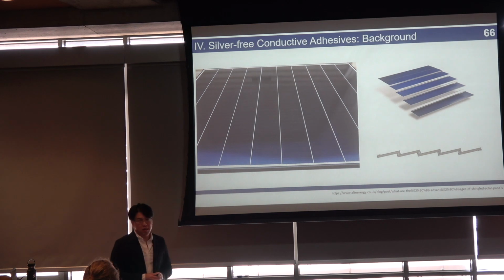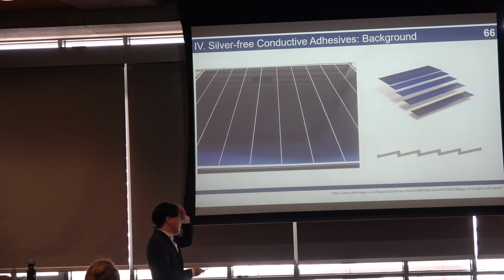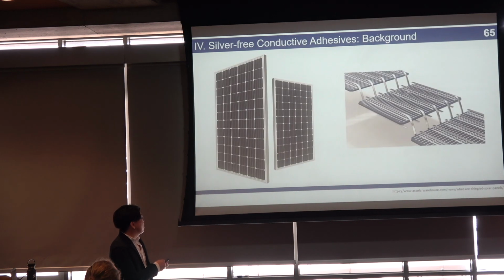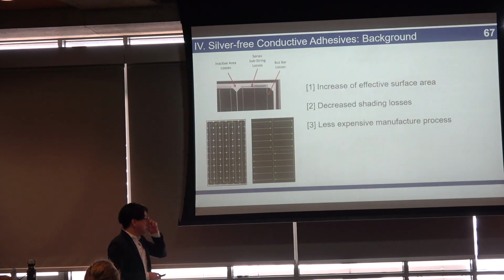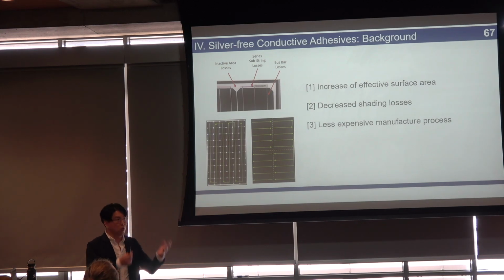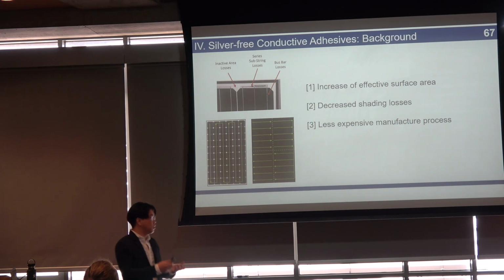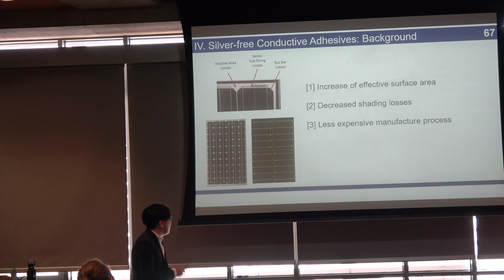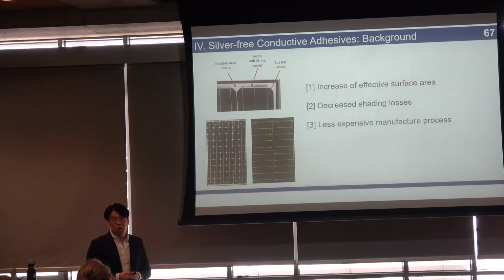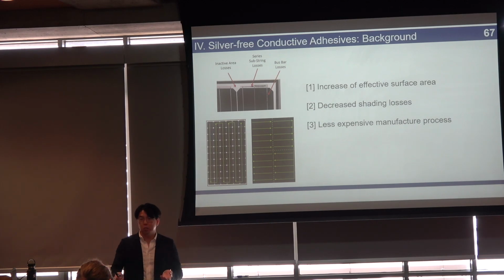In comparison, you could do something called a shingled solar cell. And basically, as the name suggests, much like rooftop shingles, you could basically overlap them and glue them together. And you might notice that there's no space between these cells compared to these. And this is pretty good, because this leads to a couple different trade-offs in efficiency. For example, it can improve the efficiency by increasing the amount of surface area. There's no bus bars to cover your solar cells, and there's no spaces in between your solar modules. You also get decreased shading losses, and because you don't have to heat your metal really hot to glue them together, you can actually have a less expensive manufacture process.